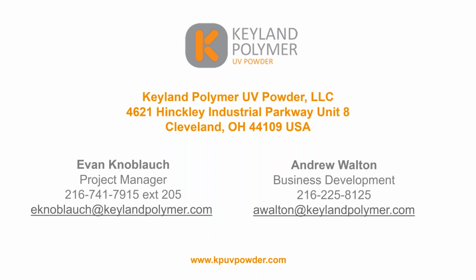What would the upper limit be in terms of final thickness of a UV powder polymer coating? We are interested in using a process for a semi-structural coating to a flexible and delicate substrate, and then to stiffen that substrate. Good question. For UV curable powder coatings, the standard film builds that we are trying to achieve for plastics and composites are typically 1.8 to 2.3 mils.